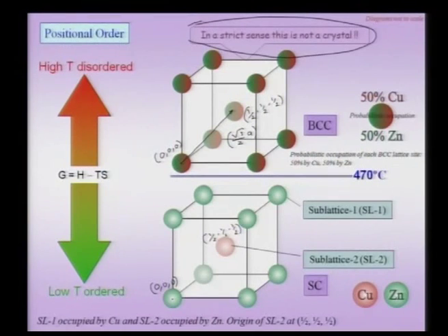So, when I go from a BCC high temperature phase to a low temperature simple cubic phase, which is now an ordered structure, the properties of the whole material will change along with it. Now, for instance, the shortest lattice translation vector would be this, which joins the 0 0 0 to 1 0 0. It is no longer the vector of the form half half half. For instance, in the BCC case the shortest lattice translation vector was the half half half vector, and in this case it will be the 1 0 0 vector.